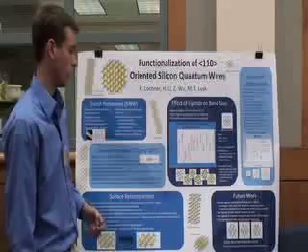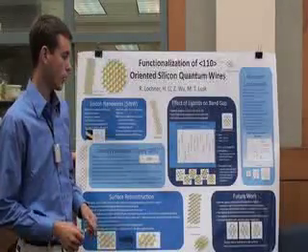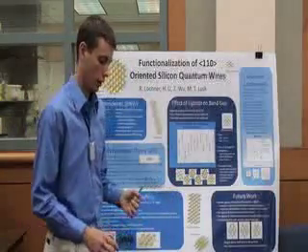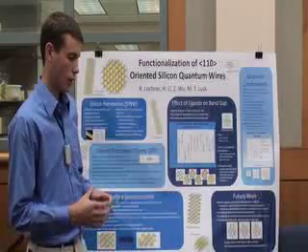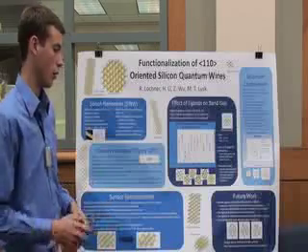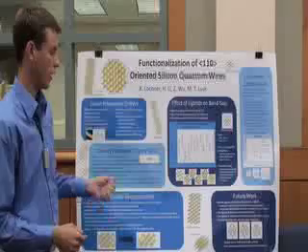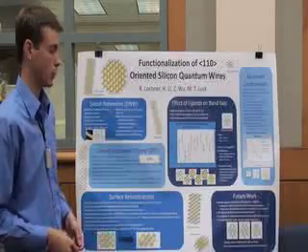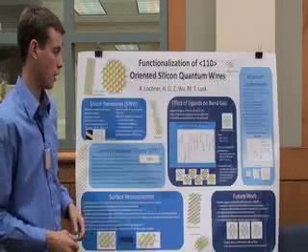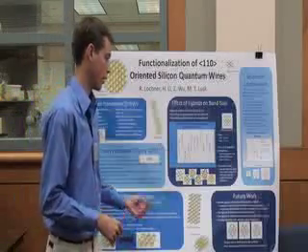I intend to move on to look at oxidation and passivation of wires, in the sense that a nanowire put in an oxygen environment, oxygen can get into the nanowire and create silicon dioxide or silica. And if that were to happen, a lot of the properties of the wire change, and the effective diameter of the crystalline silicon becomes much smaller. So in order to keep oxygen out, we're looking at passivation with different ligands.